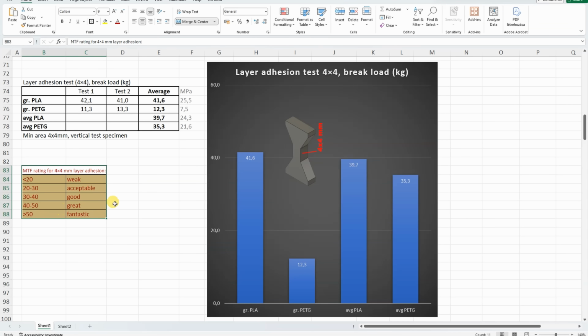According to my rating, the graphene-reinforced PLA has a great layer adhesion, very similar to the average PLA, but this graphene-reinforced PETG is very weak, and also very far from the average PETG. And a reminder, I was already printing here at the maximum recommended print temperature.